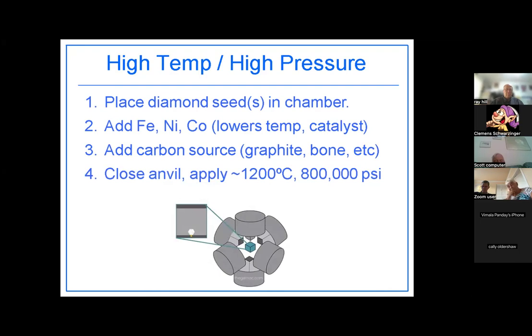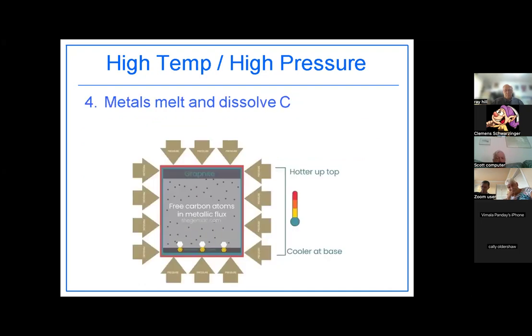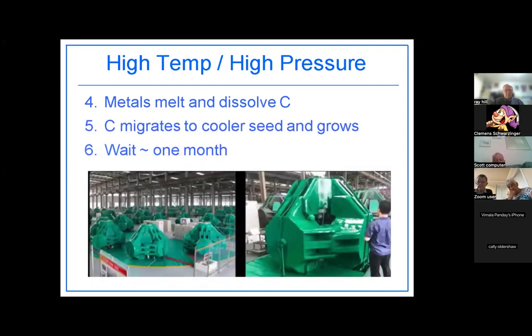And it's heated in what's known as an anvil. You see your picture at the bottom, and you can see 6 cylinders. And basically, you are just squeezing this to about 800,000 psi and 1200 degrees centigrade, and it converts the carbon in whatever material it's in into diamond. So the metals will melt and dissolve the carbon. And you can see in this picture that it is cooler at the base. So your carbon atoms migrate around until they find that cooler seed and they start growing. And then you wait about a month.